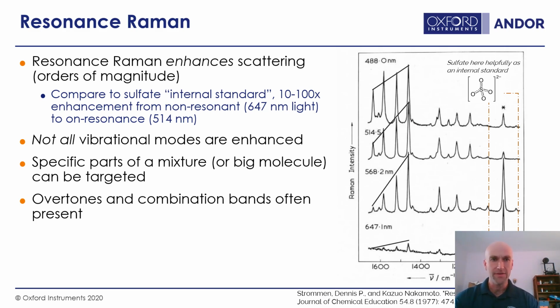However, the thing is, not all vibrational modes are enhanced, or enhanced equally. So you can see here, I tried to draw a little guide for the eye, but at our off resonance versus our pre-resonant versus our resonant here, you can see the slope of the first mode to the fourth or fifth mode changes quite a bit. It gets narrower, lower and lower slope as we go up there.